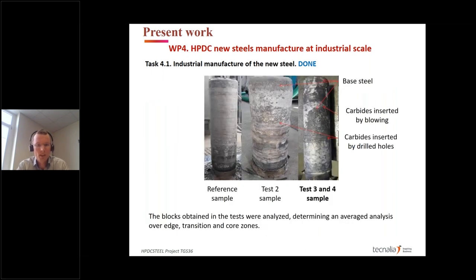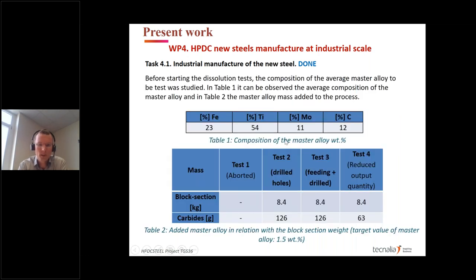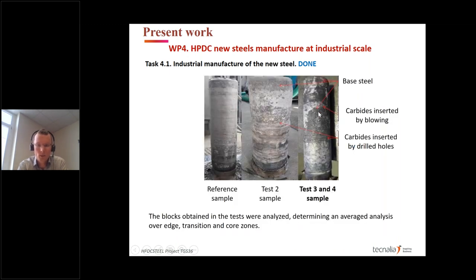successful. Here you can see some samples of ESR ingots on laboratory scale. This is a reference sample, showing how an ingot looks. The diameter is 80 millimeters. This is the second test sample, where the master alloy was implemented by the drilled holes. For test number three, we had a section-wise approach. First we had the base steel, so the electrode was untouched; we did not change anything. Then we had a part of the electrode where we fed the master alloy by a blowing procedure using ceramic tubes. And in the third zone, you can see the carbides inserted by the drilled holes over the electrode. Finally, the blocks obtained in the tests were analyzed, and we got an analysis over edge, transition and core zones.